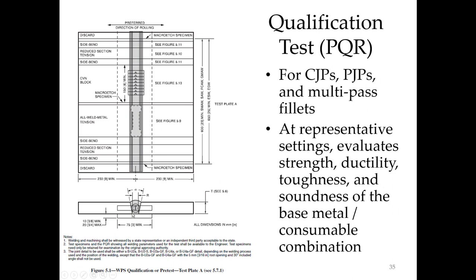To make a weld like this, and this is looking at it from the side, and this is looking in plan view, that's elevation, the fabricator would have its first pass down here in one root, and then do another root, and then do another pass, and basically take anywhere from 8 to 10 to 30 to 35 passes, depending on the process and the size of the consumable, to fill in that groove. Then the test specimens are taken, and you'll see that there's an all weld metal test taken right from the throat, and Charpys that test the throat.